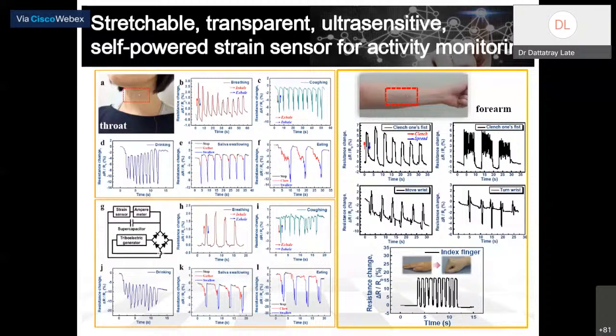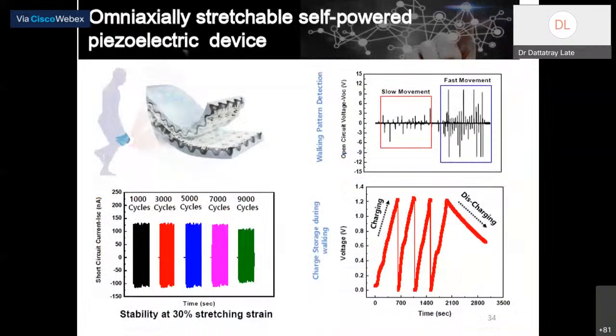Now, for example, if you want to have a self-powered device, because you don't need a battery and all these things, it will be charged on its own, depending upon your body movement. So we also tested how many cycles it can be tested. For example, we have a device again based on carbon nanotubes and the PDMS mask. We have tested how much is the change in the short circuit current. We found that after 1,000, 3,000, 5,000, 7,000, 9,000 cycles, the stability of the device is almost similar.